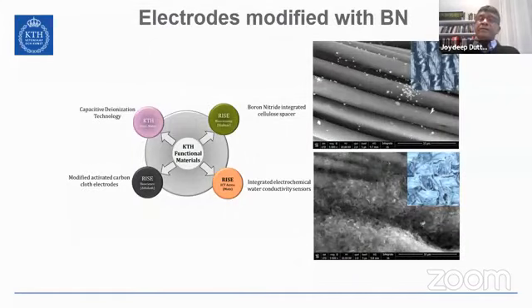Currently, we are interested in the Faraday mode. Till now, I was talking about the capacitive mode, that is where you are not splitting the water. But as soon as we start going into the Faraday mode with voltages of 2-3 volts, then one starts degrading the electrode material. So what we did was coat these fibers with boron nitride.